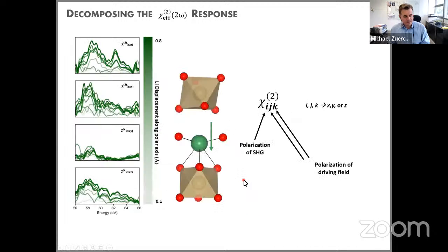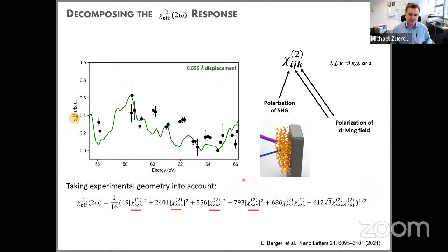Okay. I should also point out how this relates to theory. If you do time-dependent DFT to calculate the second harmonic spectrum, and that's another reason the fit may not be exactly perfect, because we know the orientation of our crystal down to 2 degrees, 3 degrees, maybe 5 degrees, something like that. We know the polarization plane of the FEL to a few degrees. So this is just assuming exactly the angles that we assume, but we don't know 100% for sure. Then what you get from the theory collaborators is that they actually calculate these tensor elements.